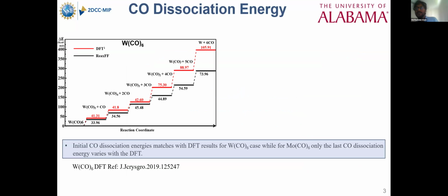Our conclusion was that the force field needs to be trained more, because the prediction we made was wrong. We didn't see any molecular structures from the deposition, so we need to retrain this force field. But in this other case, the DFT results and the ReaxFF results are not that far off, so we don't need to retrain it. But if we need more accuracy, then it's obviously better to retrain it. Okay, thank you.